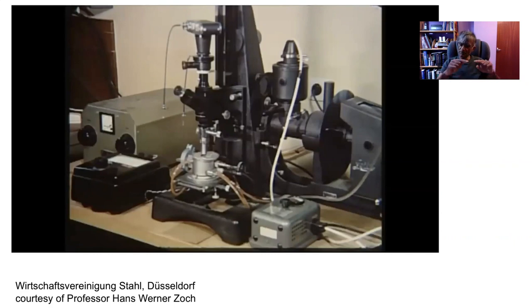It's still flat, but you develop thermal grooves at the positions of the austenite grain boundaries. When the sample is cooled, you can see the development of the martensitic transformation without any etching because of the displacements that are caused when martensite forms.